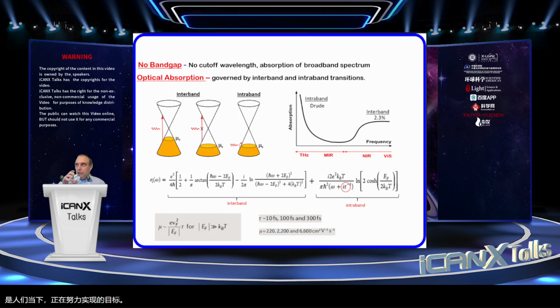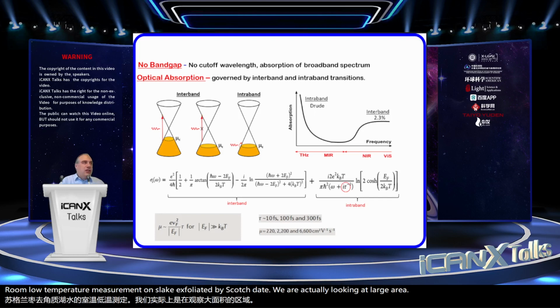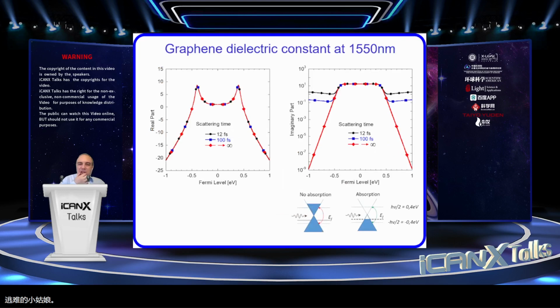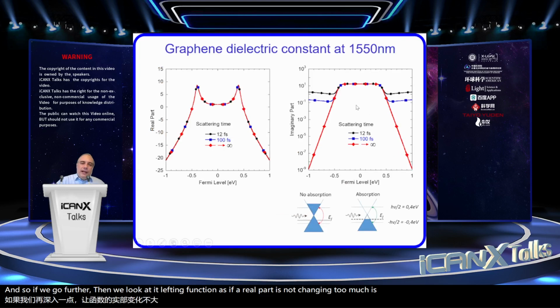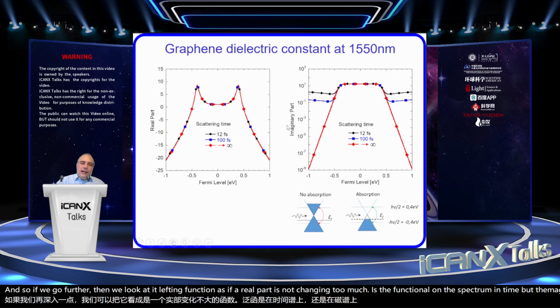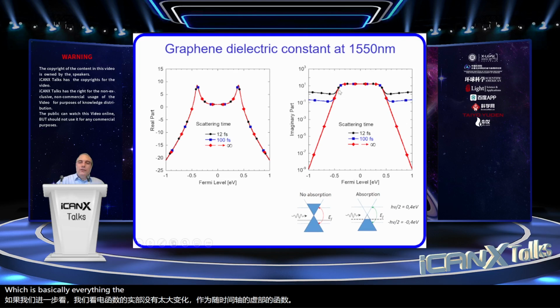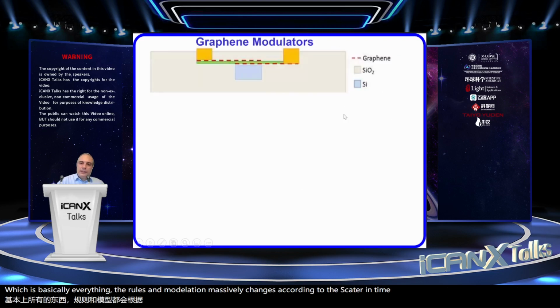Of course, we're not speaking about low temperature measurement on flake exfoliated by Scotch tape. We are actually looking at large area graphene grown on a wafer scale. And so if we go further, we look at the dielectric function, where the real part is not changing too much as a function of the scattering time, but the imaginary part, which is basically everything that rules the modulation, massively changes according to the scattering time, as we expect.